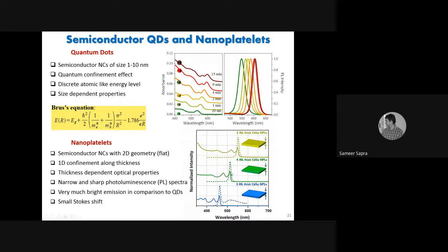But if you look at the fluorescence over here, this is roughly about 10 nanometers or even less than 10 nanometers full width at half maximum, where here you'll get close to about 25 to 30 nanometers. So this precise definition of the thickness, it's either 3, 4, 5 monolayers, and that is the confined direction. Otherwise, it is very large in the lateral directions. So you will get very, very sharp emission features, which means even better color purities when you have two-dimensional materials.